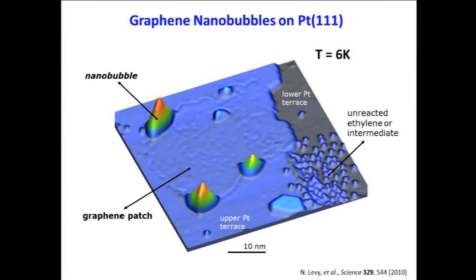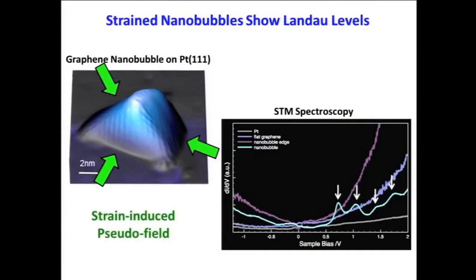We then did spectroscopy on this surface. When we did STM spectroscopy away from those nanobubbles, the spectroscopy was pretty featureless and pretty boring. But when we did spectroscopy right on top of the nanobubbles, we saw something very interesting. We saw these peaks in the local density of states appearing at different energies. So we saw these very pronounced peaks. We believe that these peaks are due to the Landau levels occurring in these nanobubbles as a result of the pseudomagnetic field that is induced by the strain in these little strained nanobubbles.